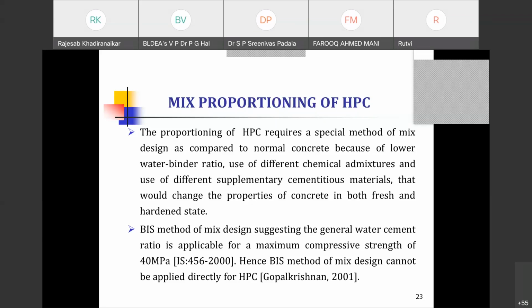And your water binder ratio also depends on your size and texture. So normally they go for 20 mm downside, but the better suggestion is 10 to 12 mm. In some cases, you can also go to 20 to 25 mm, but in that case, the strength will be lower. So you have to properly understand the effect of each of these properties, and then choose the aggregate based on your strength requirements.